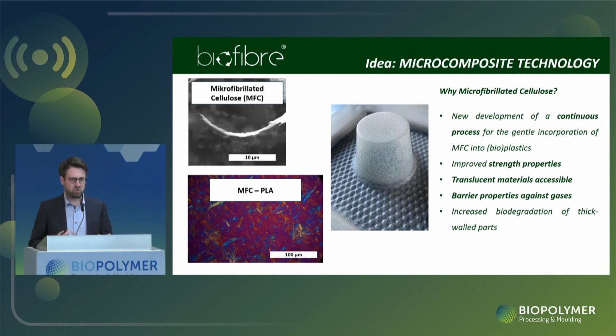So for those of you who are familiar with MFC, or microfibrillated cellulose, it's certainly no secret that they are quite hard to handle. They are most of the time in the presence of water, like suspensions. You can go up to 30% of solid content in those suspensions that are dosable and pumpable. But if you are using this in a conventional extrusion system, you very quickly see something like a steam engine, and you generate a lot of moisture and a lot of gas and vapor.